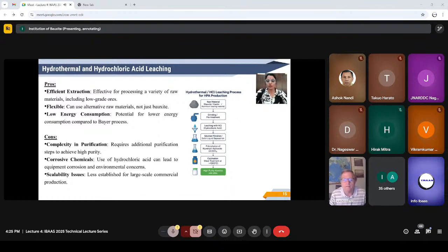So the powdered material is then subjected to leaching using HCl under controlled temperature and pressure conditions. This is either done at atmospheric pressure or in hydrothermal reactors. So this step dissolves the aluminium content into the solution, leaving behind most of the impurities as residue. Next, the leachate is filtered to separate solids from the acidic aluminium-containing solution.